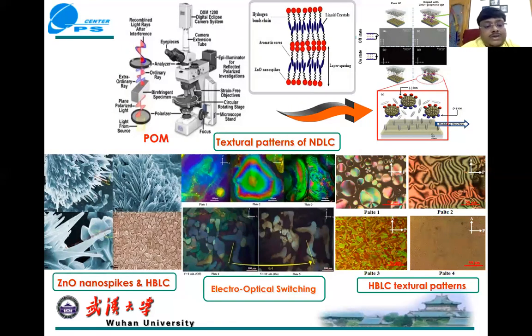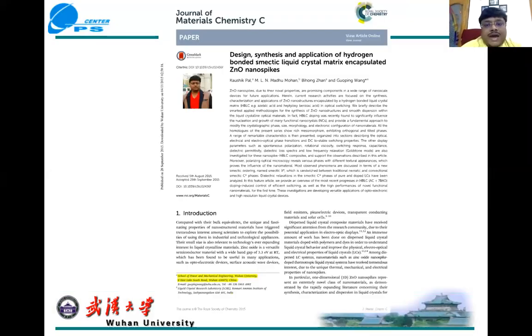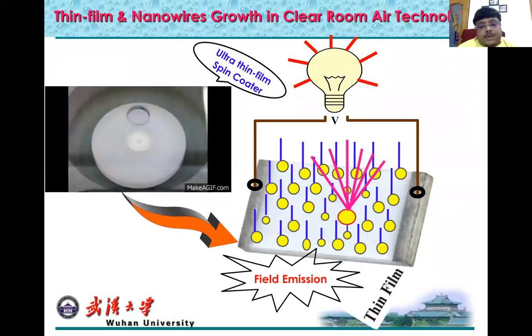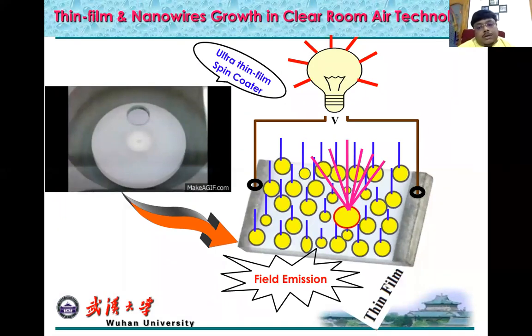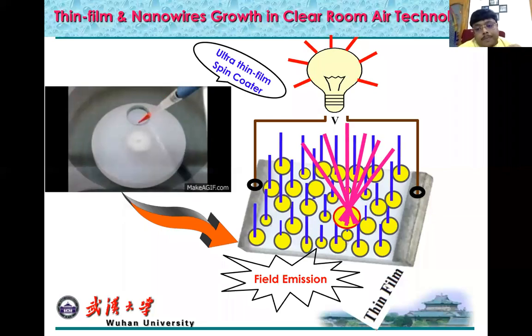We started with zinc oxide nanospikes, and here is a worm-like structure. You can see the HBLC, hydrogen bonded liquid crystal, so we mix the compound matrix. Okay, so the Royal Society of Chemistry appreciated our work for the nice switching device. And this is another system where we can make aligned structures by spin coating, using a programmable spin coater. We use a thin film and grow from a seed particle layer. In the seed layer, there are highly, vertically aligned nanowires.